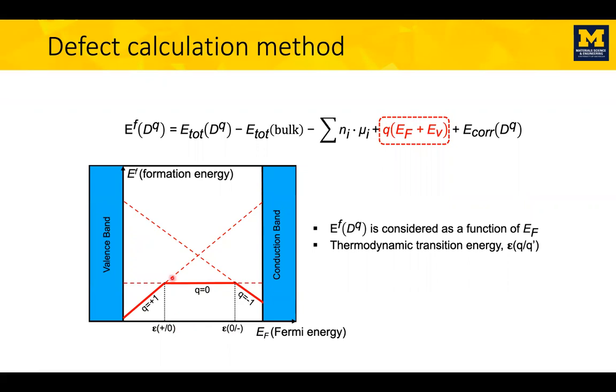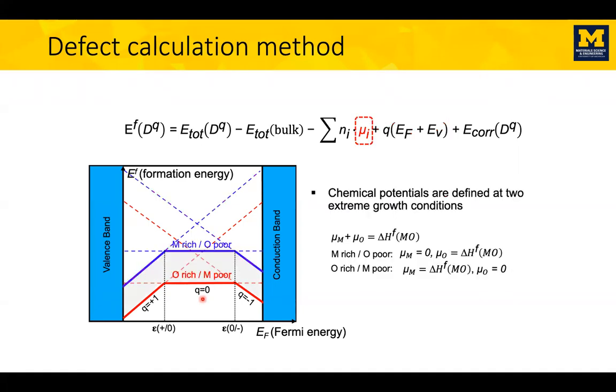So we have these transition points where the defect changes charge state, the thermodynamic transition energy, and that corresponds to the energy we need to pay to ionize the defect. Okay. So that's one thing we'll see here. The other thing is that if we change the growth conditions, the chemical potentials of the species that we exchange atoms with, we can change the formation energy. For example, oxygen defects are more likely to form if you grow under vacuum than under oxygen. And the same with a metal. If you grow under oxygen-rich conditions, you are more likely to form a metal vacancy because it's metal-poor conditions than if you were to grow under metal-rich conditions. If you have excess metal, you're going to fill those empty spots more easily.